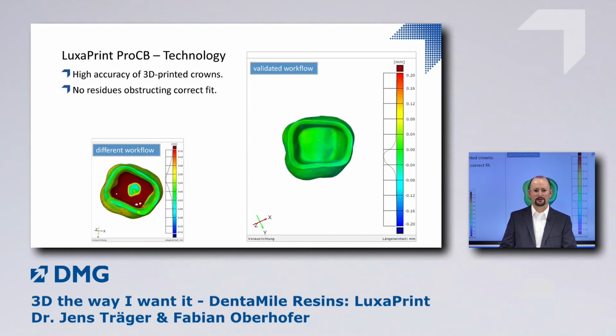You could basically avoid this white layer we've seen on the slide before by just wiping off the residual resin with a cloth or a brush or something similar, but you would never know if you have really thoroughly cleaned the object. And it's a rather high risk that residues of resin could stay on the inside of the crown, which is shown in this picture. Red color means that there is a positive difference, so too much material compared to the original digital object to be printed, and this could of course give problems when fitting the crown. So when there's too much material on the inside, the crown could not properly fit on the tooth stump when trying to cement it.